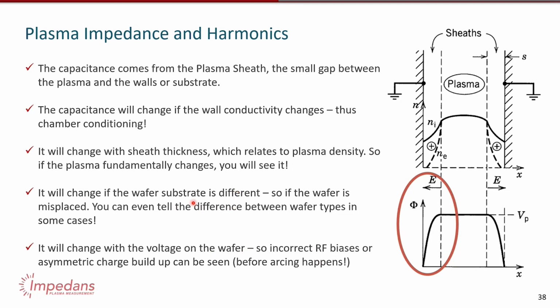Another application actually is, because the wafer has a capacitance, if you're depositing on it or you're etching it, you're changing the capacitance. So that means that by monitoring the RF, you can actually monitor the progression of etching or the progression of deposition, which enables endpoint detection. So I'll show examples of that later as well.